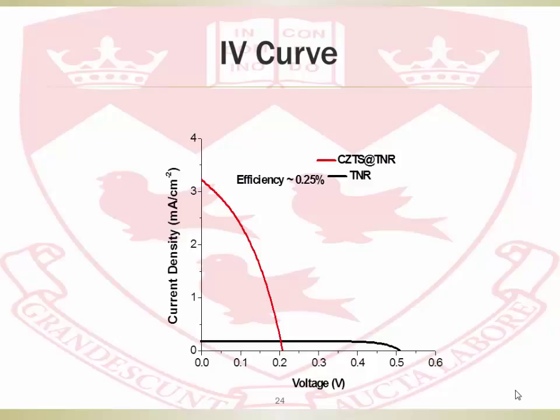The poor fill factor could have different reasons: shunt resistance and series resistance are not optimized, and there are many recombination centers. Also, CZTS is generally a P-type semiconductor and when combined with titanium oxide, it's not like cadmium sulfide or widely investigated quantum dots where both are n-type. There's no large band alignment, so there could be charge migration issues at the interface, leading to decreased fill factor. We should address these one thing at a time.